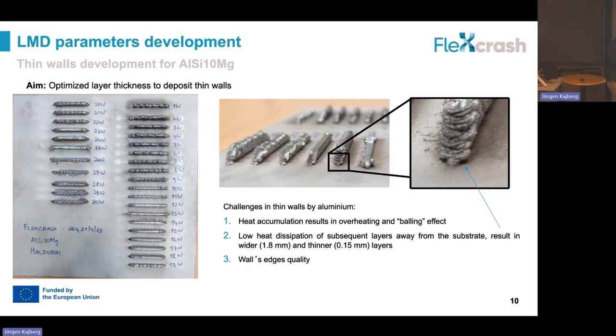With the close-up of the deposition, we could notice already from the beginning that the first track we deposit on the substrate is quite thin, but already from the second track on, we had this effect of the tracks getting thinner and wider.